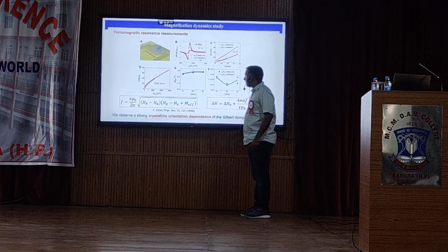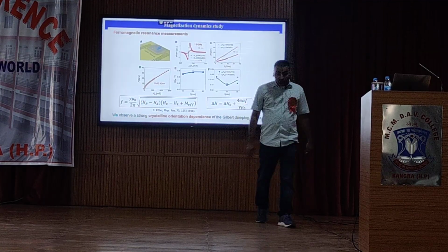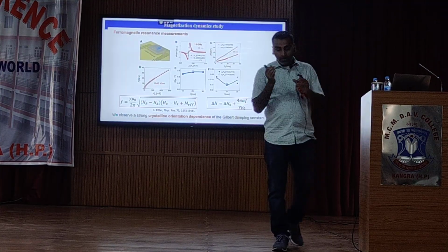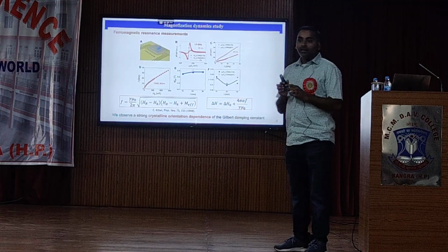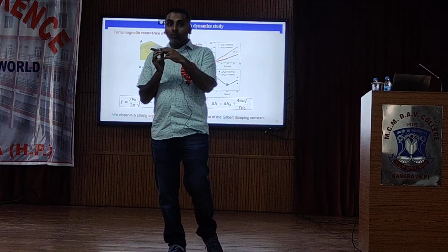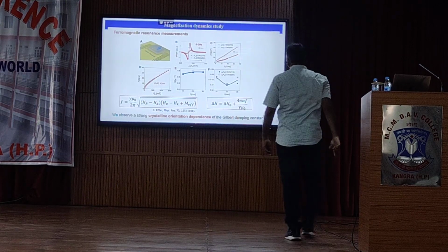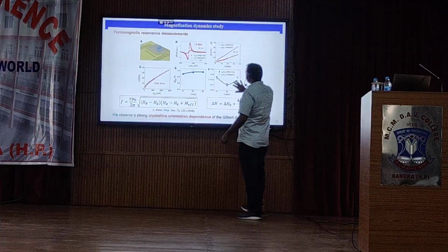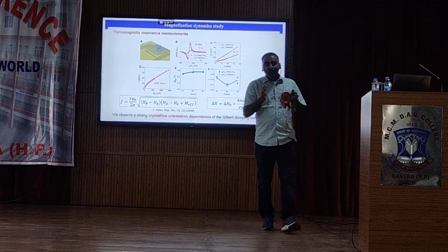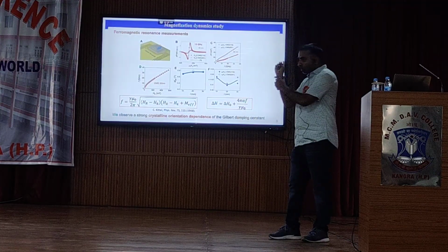As you can see from our analysis, we see a very low magnetic damping constant, which is a very important factor when we consider power consumption, because as I explained in the beginning, if the magnetic damping is higher, magnetization will try to align in the direction of the field very quickly. We need more current to balance the damping. The damping parameter, which I defined with alpha, is equivalent to the current we need to compensate for that. If this parameter is low, then we need low currents to balance the damping, which is causing the magnetization to align in the direction of the applied magnetic field.